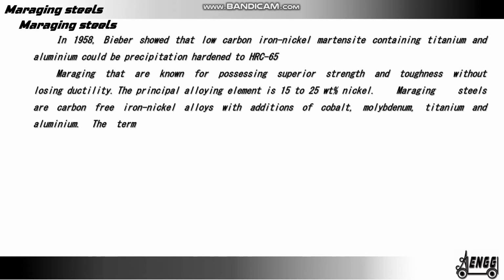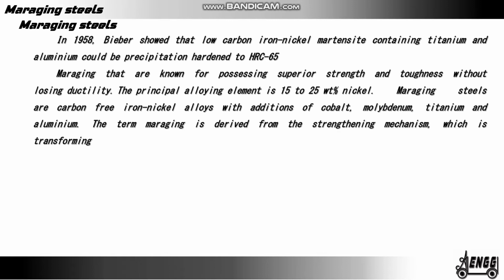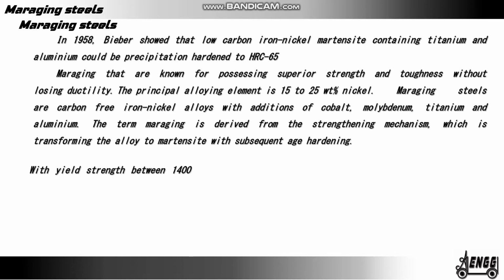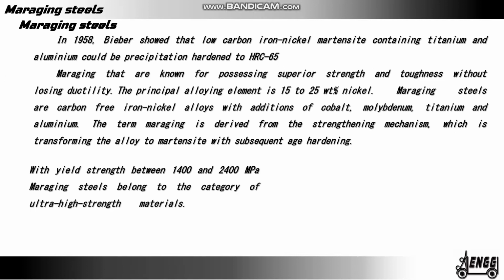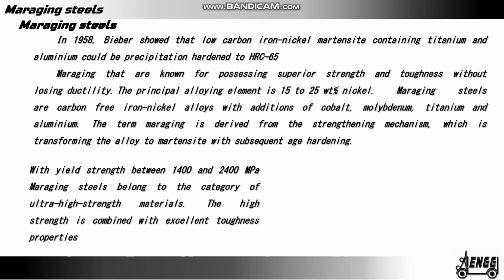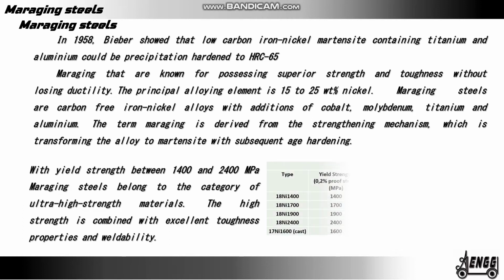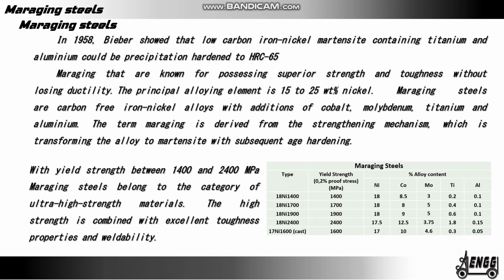The term maraging is derived from the strengthening mechanism, which is transforming the alloy to martensite with the subsequent age hardening. With yield strength between 1400 and 2400 megapascal, maraging steels belong to the category of ultra high strength materials. The high strength is combined with excellent toughness properties and weldability. In the table we can see the different types of maraging steels, their yield strength and percentage of alloy content.